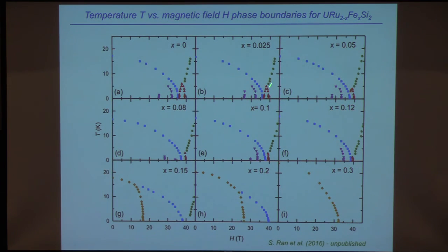These blue lines are always the suppression of the hidden order phase. This is the metamagnetic transition. These red ones are one of these quantum phases, and the purple one might be a new quantum phase that we found in this system. Okay? As you increase the iron concentration, all of these are in the hidden order regime, and you see similar features. Then you cross over into the antiferromagnetic regime, and you lose those quantum phases. Here, for example, you find that you suppress antiferromagnetism, and then hidden order grows out of it, and then you get the metamagnetic transition, but none of the other phases.